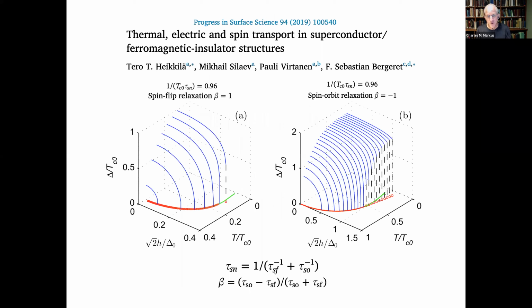I'll kind of fast forward to an important review article from 2019, which considered, and I apologize for going faster than I should. It, of course, is not my work, and I want to get onto the experimental aspects, but it's complicated. How this gap, just as an example, this is what we looked at already. Here was as a function of temperature in units of the transition temperature. So here's zero temperature. And you see that the gap is first order until it goes bonk. That's what I described before.